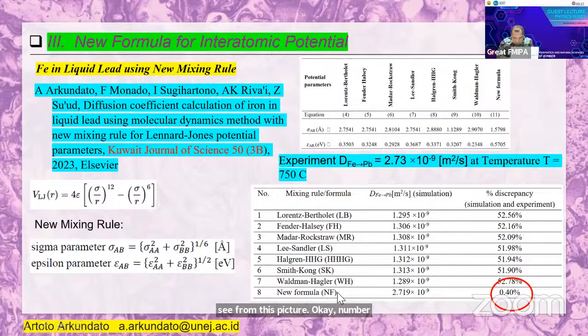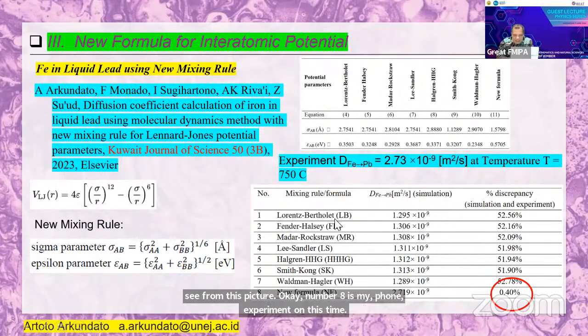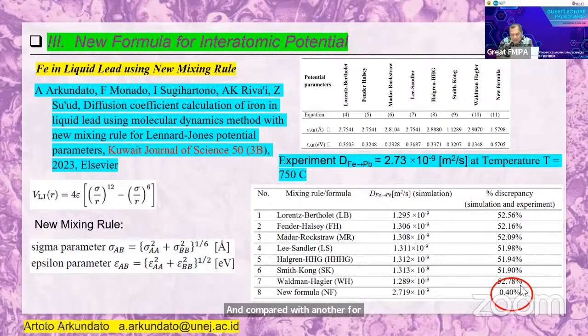Number 8 is my formula. Compared with experimental result, and compared with another formula, my formula is very accurate. It only has a discrepancy or error of about 0.40% compared with experiment. Compared to another formula that has a discrepancy of about 50%, it's very big, and so our formula gives a very good result.